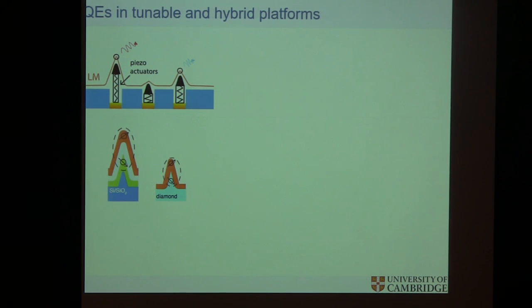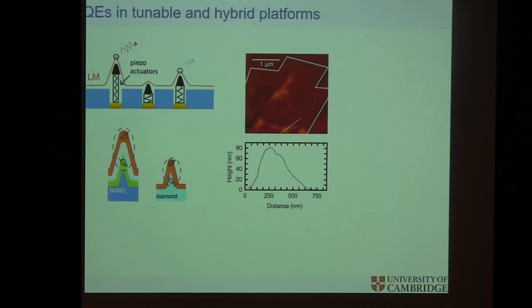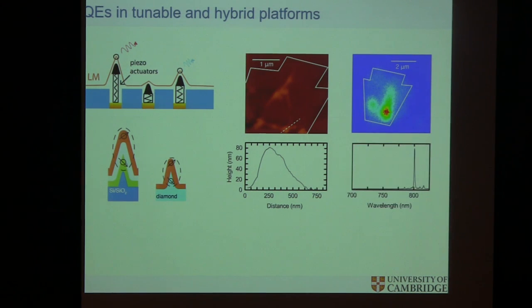And again, the question is, well, is it silicon oxide dependent, or can it be any arbitrary system? And here is nanodiamonds, silicon oxide and nanodiamonds together. And this is the AFM profile. And if you look over there, with the flake on top of it, then we get the emission. So we can create confined excitons, quantum dots on top of nanodiamonds, nice sharp emission peaks. Of course, that nanodiamond didn't have any spin, so this needs to be done more properly, but you see the concept.